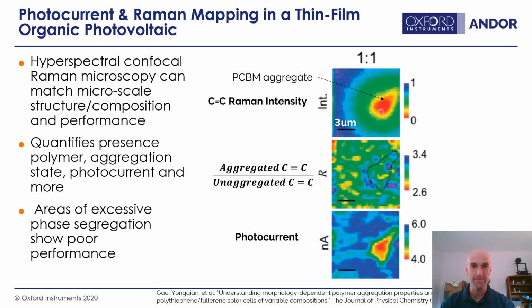But we can actually see the metrics of order and disorder in that polymer, as far as the aggregated versus unaggregated carbon double bond Raman peak. So we can look and actually see how that polymer is arranged around different areas, and you can see that the aggregated is higher here and less high here. And furthermore, you can actually see the photocurrent from the device. So the photocurrent is actually worse in areas where segregation has become too high, which kind of makes sense in that you need as much interface as possible to do efficient charge separation and then get that out for use in the device.